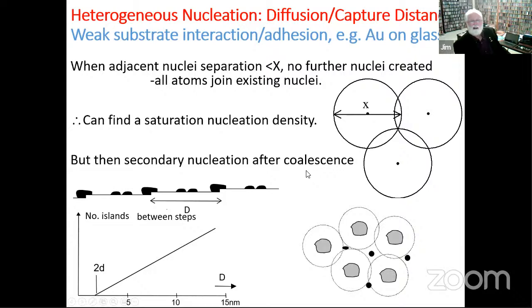The reason that the islands are created is that the atoms migrate, as I said, then they form a capture distance. And this diagram here, you could see any atom that lands in here is going to be captured either by this island or this island. And then finally, as you can see here, with the coalescence of these islands, they might coalesce together and leave an open area here where the new island can be created.